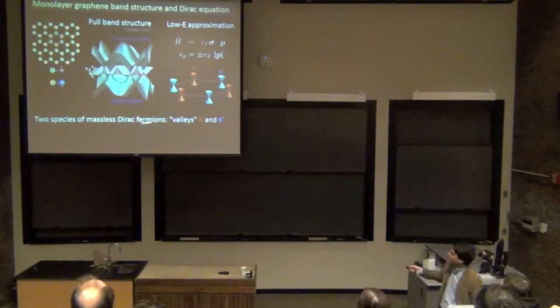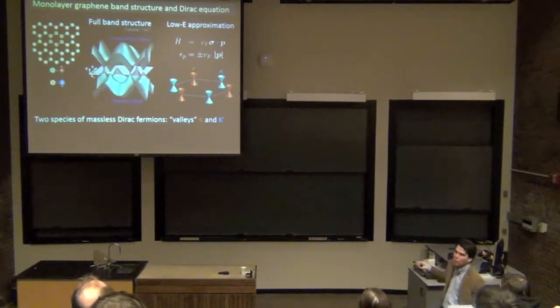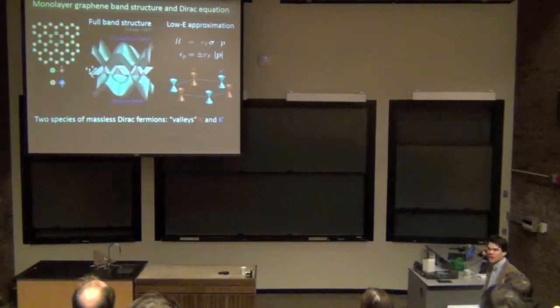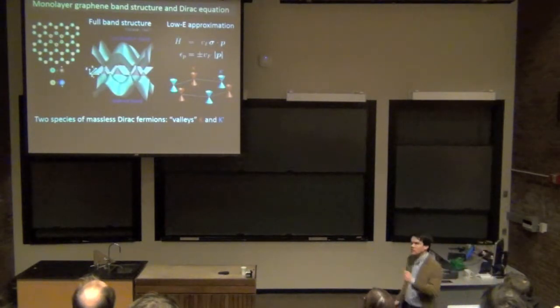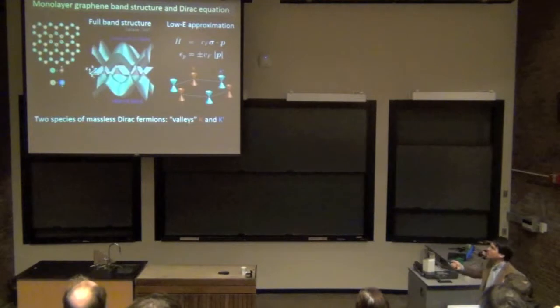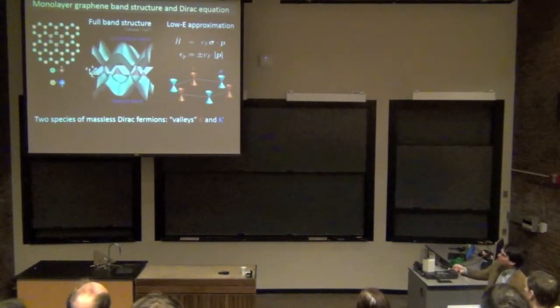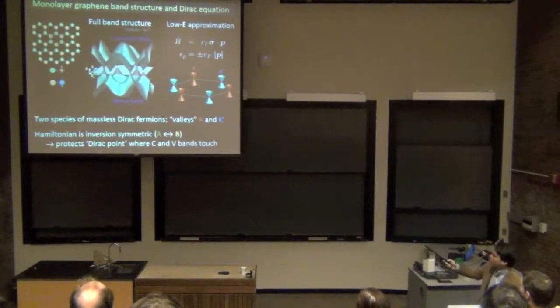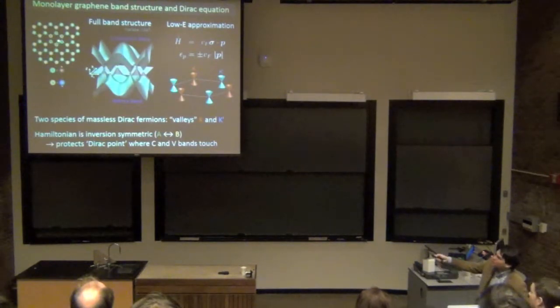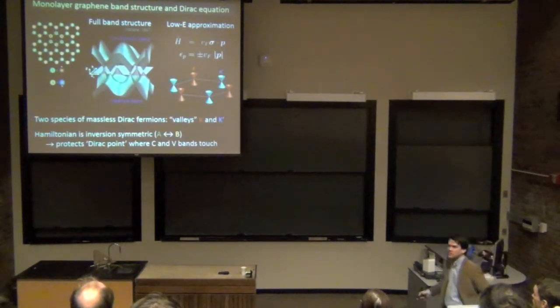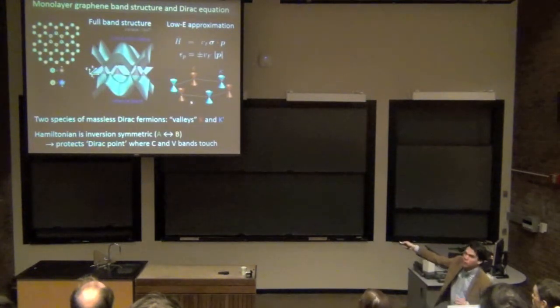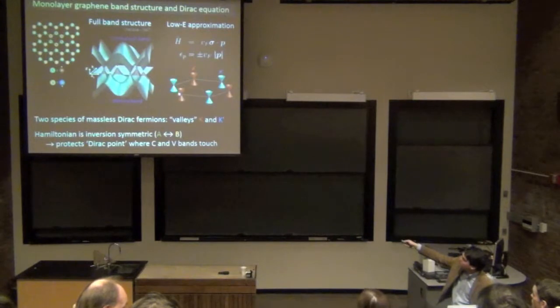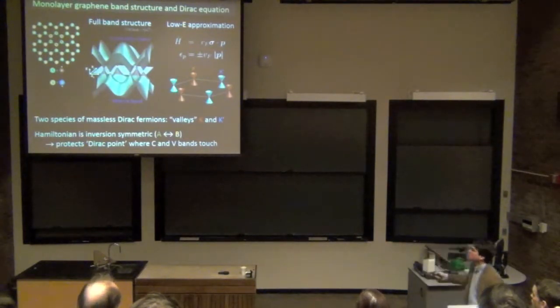And these massless Dirac fermions come in two flavors. It's because basically these two corners here are inequivalent. So you have a valley K and a valley K prime, so called. And so there's an additional quantum number known as the valley quantum number of these electrons, in addition to the normal electron spin up or down. So there are these fourfold degenerate levels in graphene. And maybe most important for the rest of this talk, this Hamiltonian here is actually inversion symmetric with respect to interchange of A and B. And that's a very important point, because it means that this so-called Dirac point here, the point where the conduction and valence bands touch, is protected by a symmetry of the system.